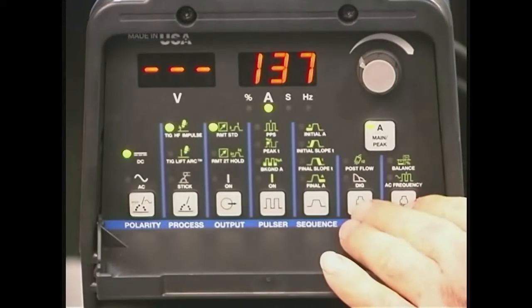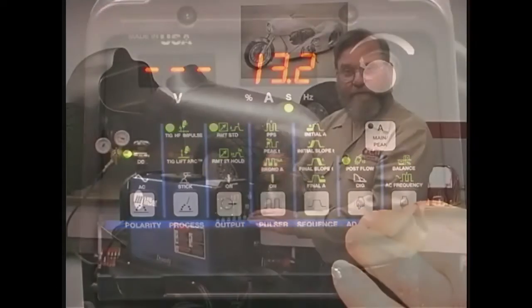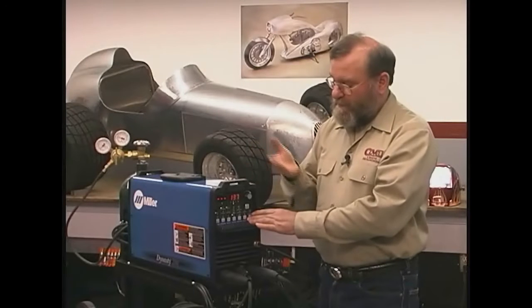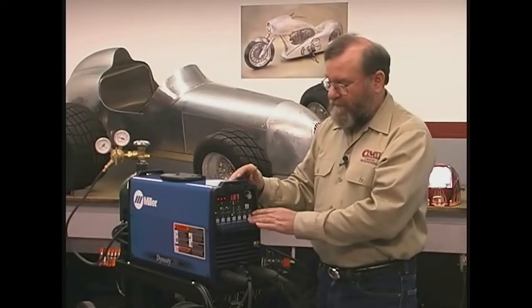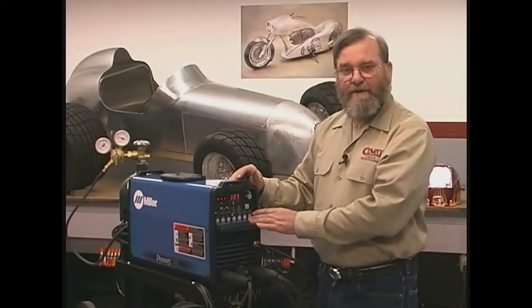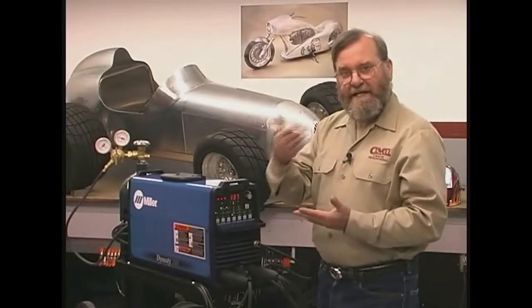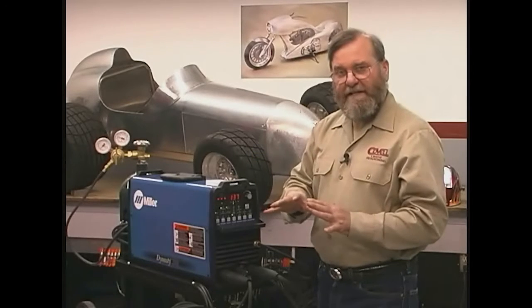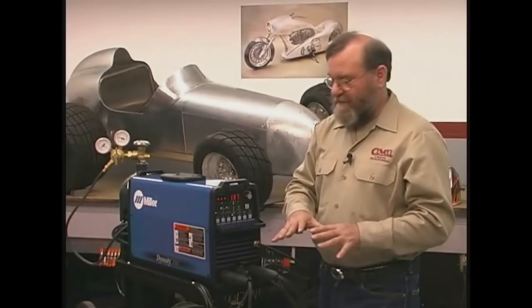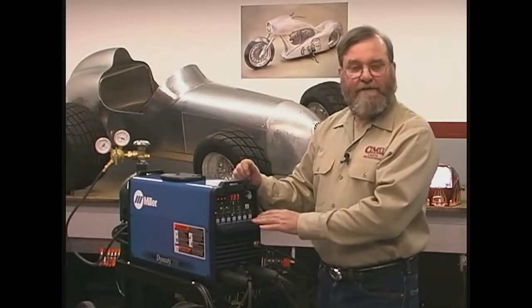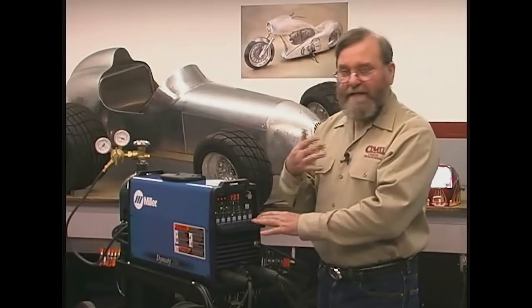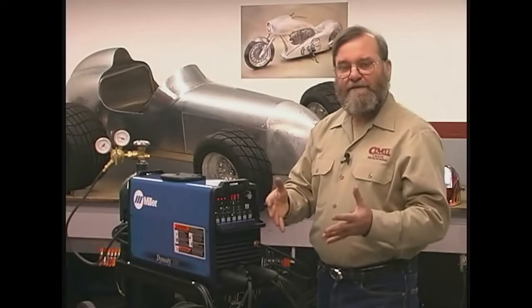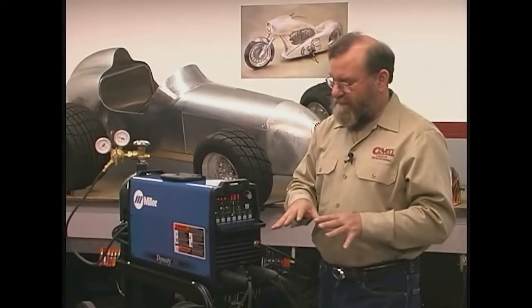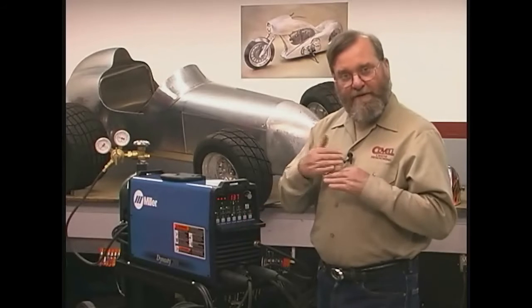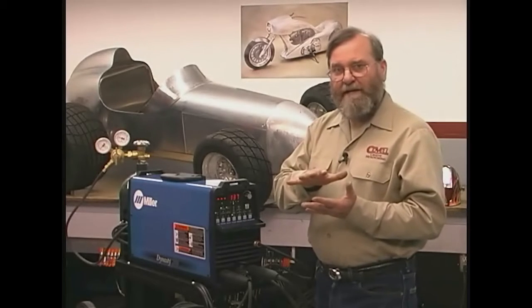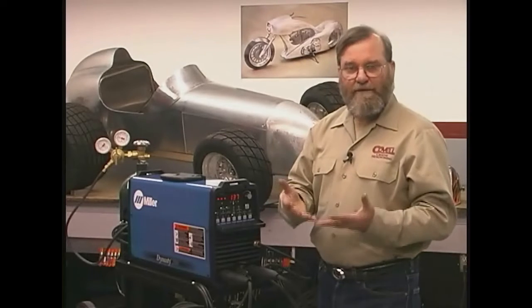The next button is used to set pre-flow and post-flow. Now, pre-flow I'm going to do in a manual manner, so we don't need to use the automatic setting for pre-flow. Post-flow is different. What we're setting with post-flow is the amount of time that gas continues to flow over the electrode, shielding it as it cools down after the welding current has stopped. Without any post-flow, the electrode oxidizes immediately, and then the next time you weld, the oxides break off the electrode and they contaminate the weld pool. This is very bad. So we need to have enough post-flow to shield that glowing red electrode until it cools enough that it won't oxidize.